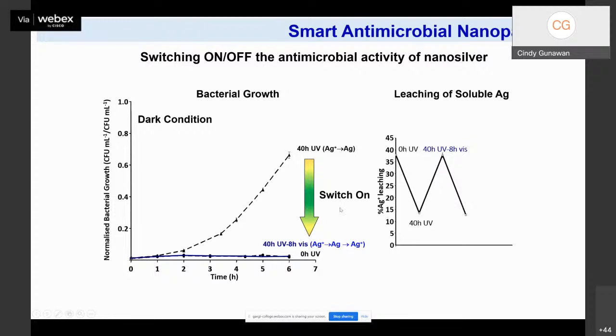Okay, lastly, we have switch off and switch on, and we would like to see whether we can go a full cycle of switching off the antimicrobial activity again. So we took these nanoparticles and exposed them to another round of UVA illumination, which means that the silver(I) deposit is reduced back to metallic silver, and accordingly we could see this switching off of the antimicrobial activity in the growth profile. And in line with this, we could see a drop in the leaching of soluble silver.